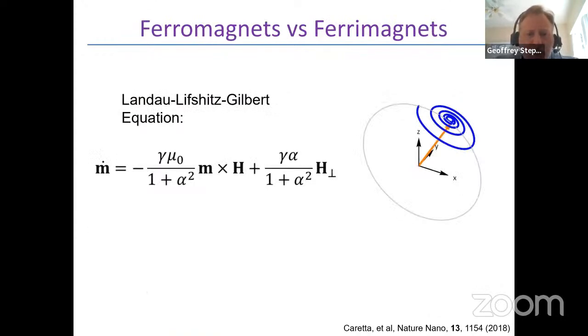When one goes to multi-sublattice materials, so compensated ferrimagnets or antiferromagnets, one can recast the LLG equation in such a way that the gyrotropic term vanishes. And I won't go through the details of this, but typically, in a ferromagnet, when you apply a magnetic field, the magnetization will precess around that field and eventually will damp towards that field direction. But it's somewhat of an indirect drive process, an indirect switching process. And that precessional motion is responsible for things like skyrmion Hall effect and Walker breakdown and so forth.